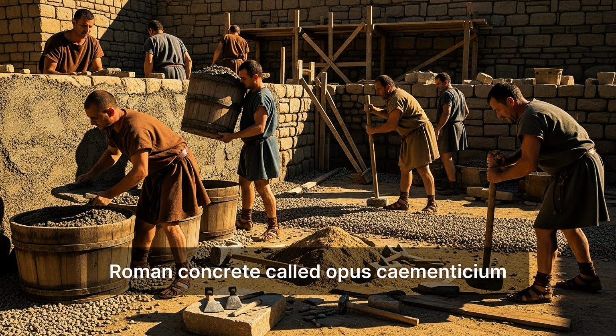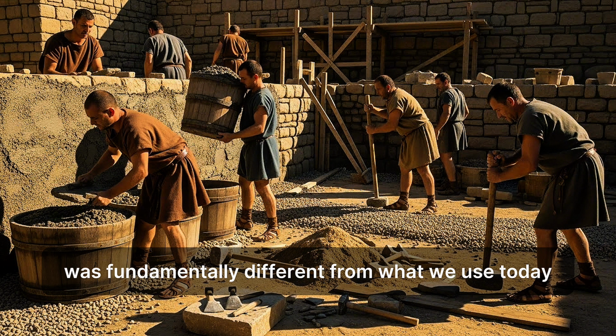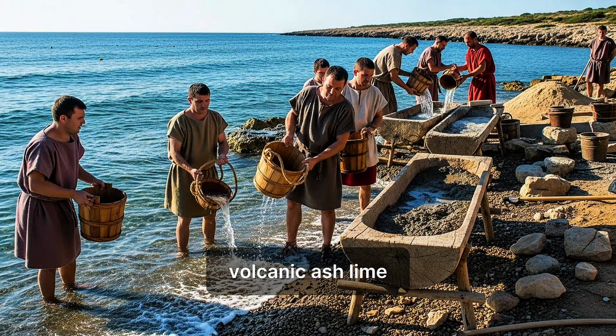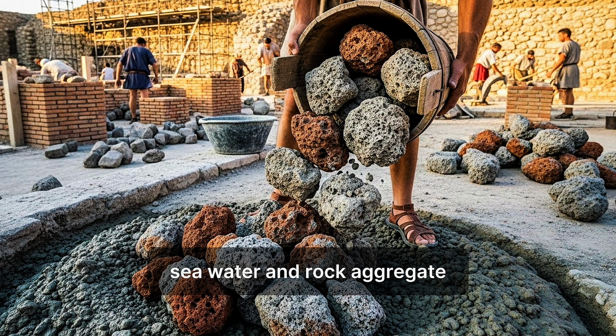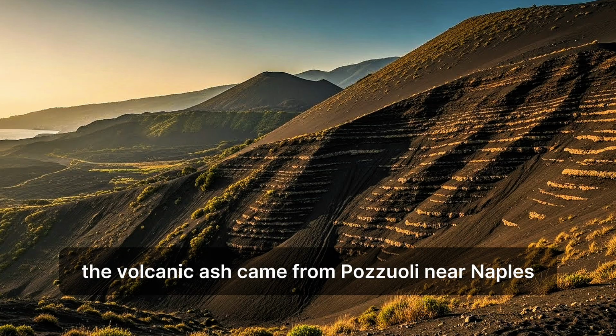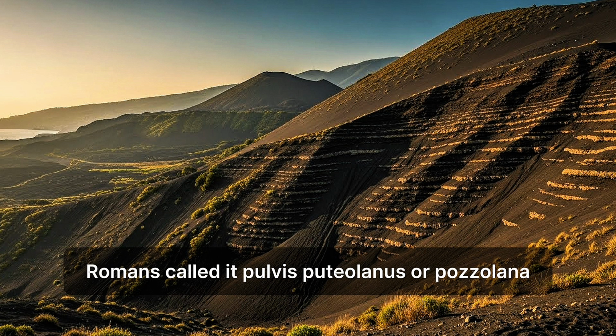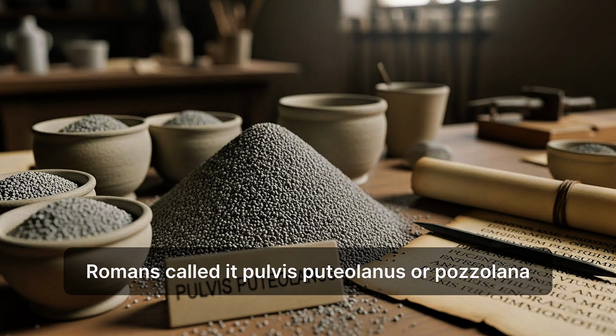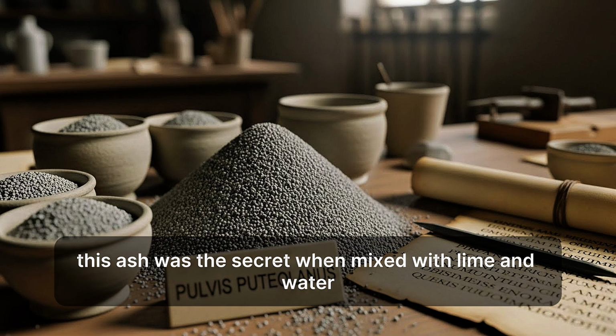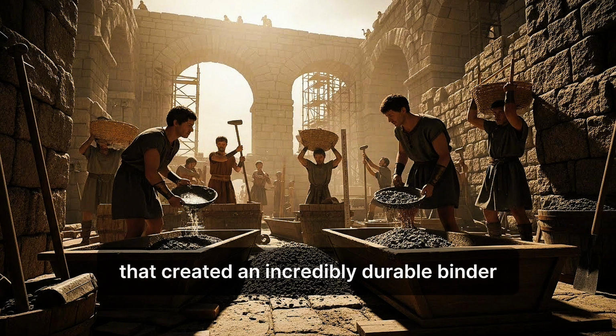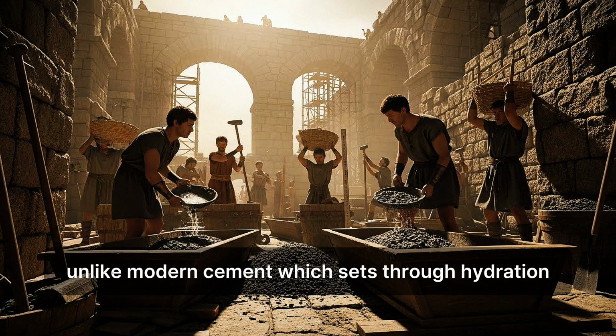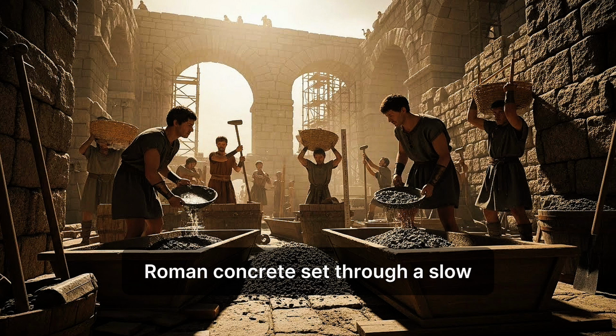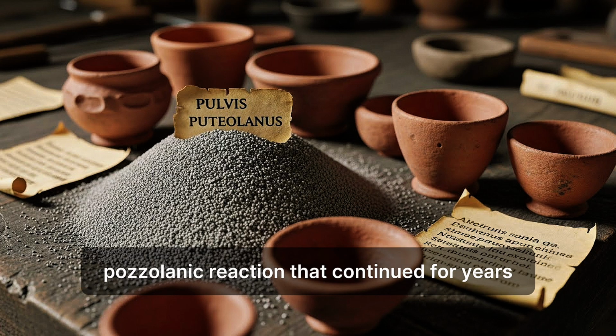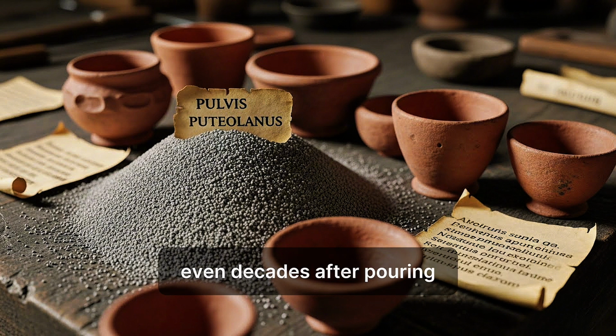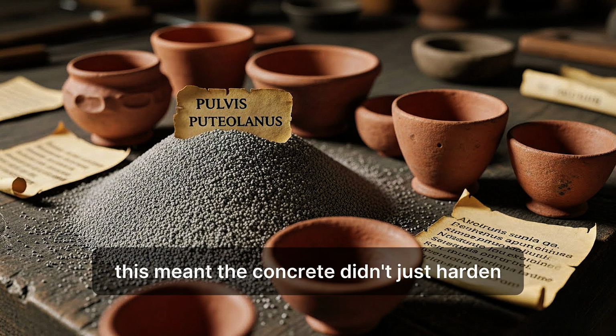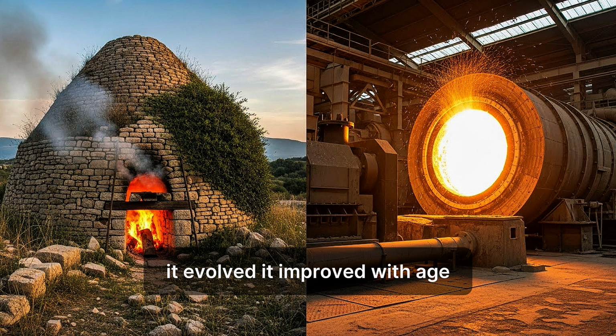Roman concrete, called opus caementitium, was fundamentally different from what we use today. The recipe was simple but precise: volcanic ash, lime, seawater, and rock aggregate. The volcanic ash came from Pozzuoli, near Naples, a region rich in volcanic deposits. Romans called it pulvis puteolanus, or pozzolana. This ash was the secret. When mixed with lime and water, pozzolana underwent a chemical reaction that created an incredibly durable binder. Unlike modern cement, which sets through hydration, Roman concrete set through a slow, pozzolanic reaction that continued for years, even decades after pouring. This meant the concrete didn't just harden. It evolved. It improved with age.